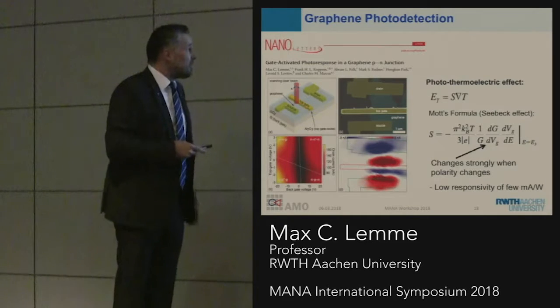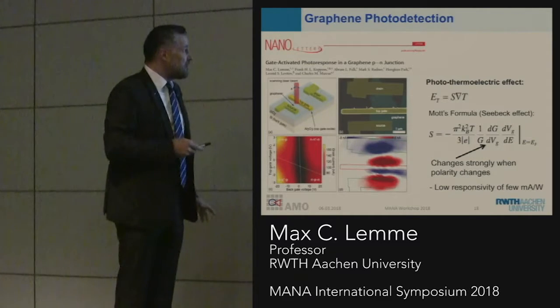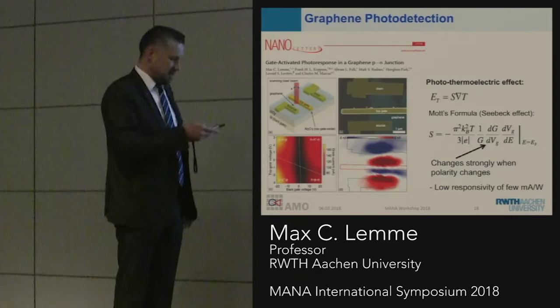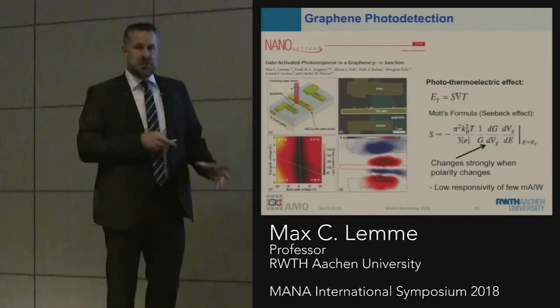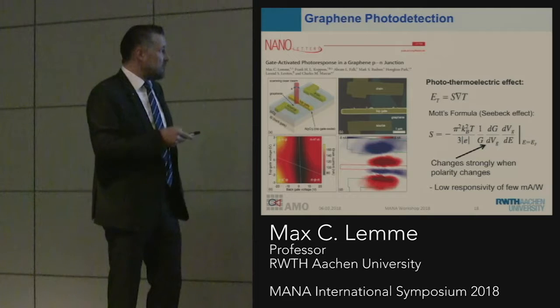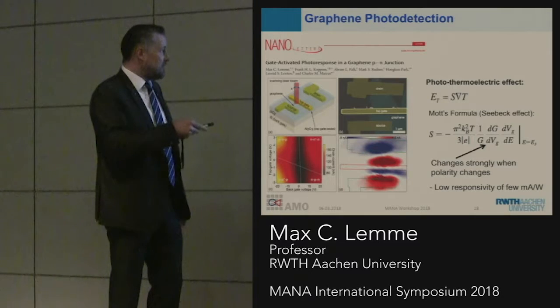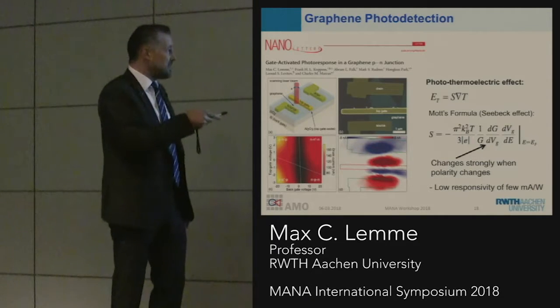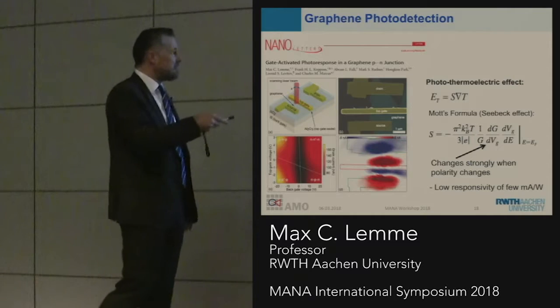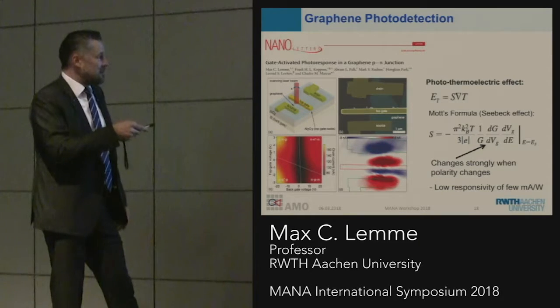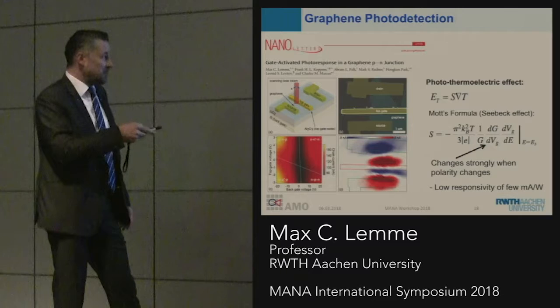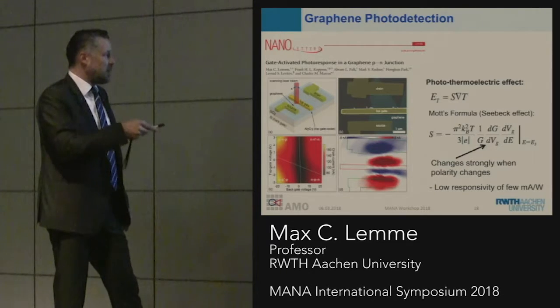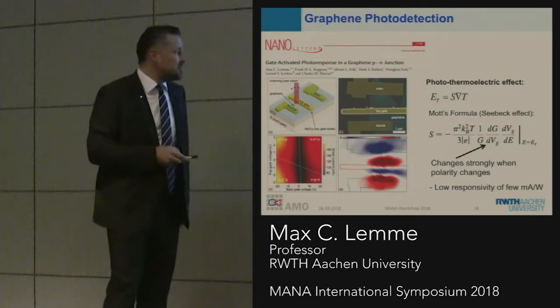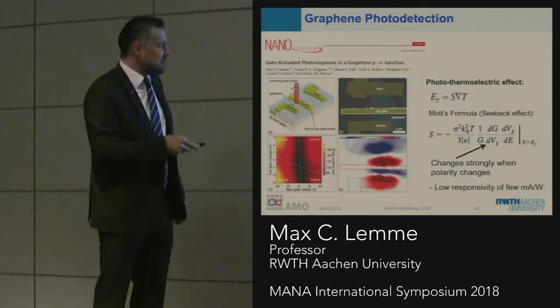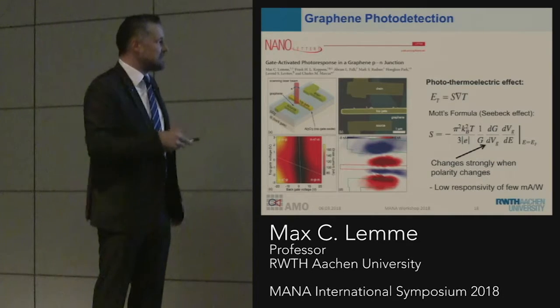Some early work I did when I was still working in the US was this, where we looked at scanning photocurrent measurements of graphene. We made a device with a top gate and a bottom gate, and this blue area is the graphene. By scanning a laser beam across this whole surface, we looked at the active areas - where was the most photoactive region?